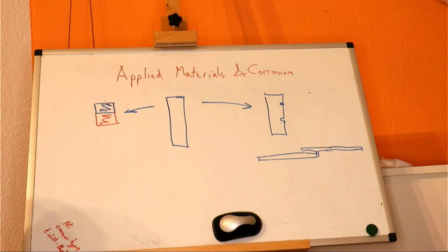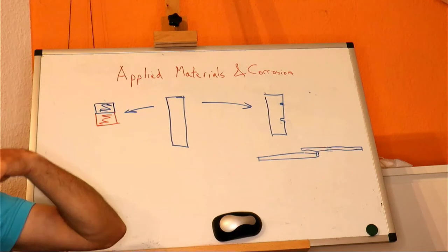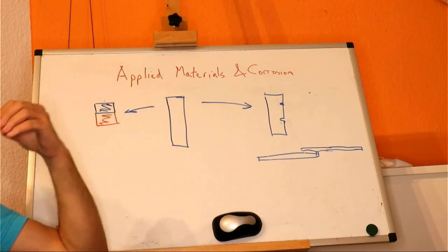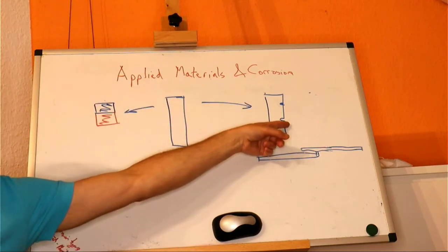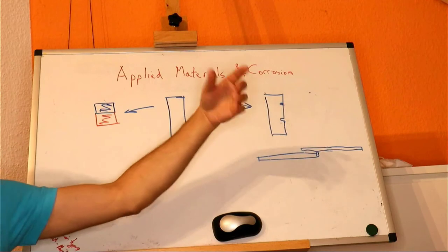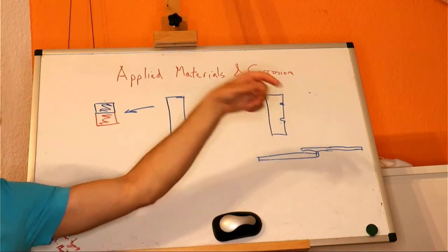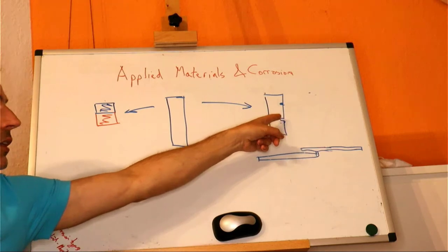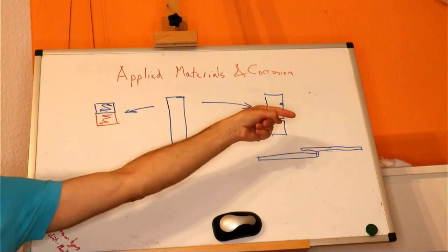But zinc does this on its own. If we start to make a little pit in our surface and it becomes anoxic, that becomes lower in pH, because here we're generating OH- the whole time, and here we are not generating OH-, we're generating Zn2+. And as we look on our Pourbaix diagram, we can see that if it's acidic, our zinc will stay dissolved, and so a hole doesn't get plugged up. It might get plugged at the outside, but it's unlikely to get filled up at the bottom where it's acidic, and so the zinc ions will move out, and